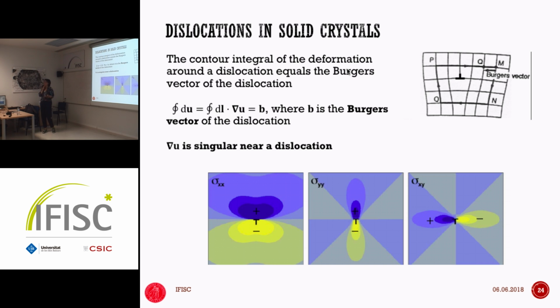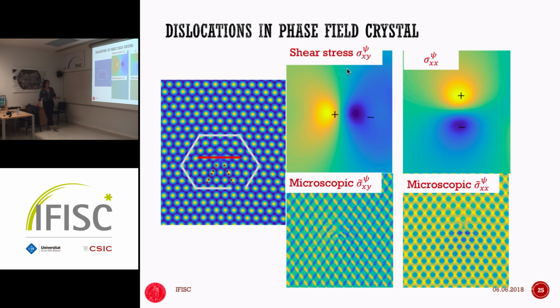Unlike for vortices, where the charge is actually a phase, so it's a scalar, for dislocations the charge is a vector. It tells you the amount in lattice units that you need in order to close the loop. So mathematically, if you have this deformation field and you do a loop around it, and that loop encloses a dislocation, the integral is going to be non-zero, and the value of this contour integral is directly related to the Burgers vector. So that's the definition of a topological defect, because it's a local feature that has topological properties. So do we see the same thing in our model? That's the question. And we do.